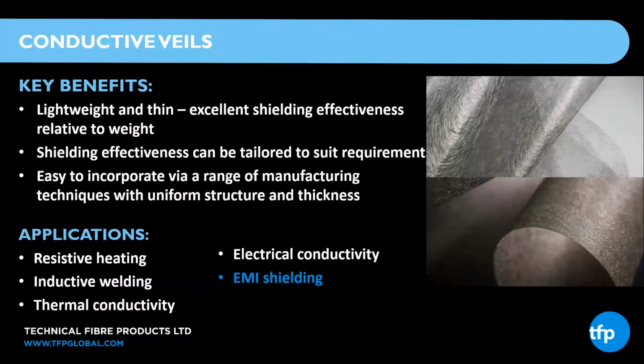So the application we're talking about today is EMI shielding. However, I should also point out a few others. Our conductive veils are used for resistive heating. Similar to the way a toaster works, if you run current through our metal coated veils, they will heat up. An example of that was in a video that Neil showed a few slides back, where the Technofire expanded. That was because there was heat caused by the current running through the material. Another application is inductive welding, thermal conductivity, or electrical conductivity.